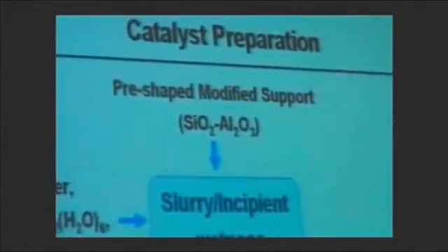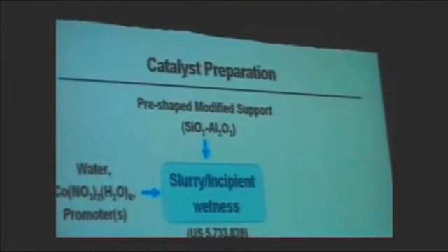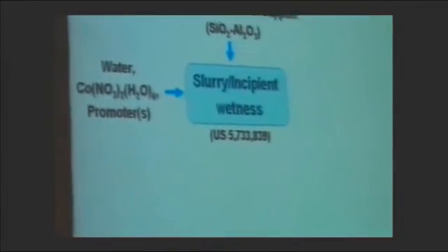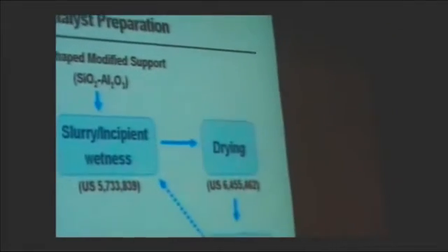Typical way of how you can prepare a catalyst, you start with your pre-shaped modified support, bring that in contact with your cobalt 2+ source, which in this case is cobalt nitrate hexahydrate, through a slurry or incipient impregnation mode, followed by drying and calcination, and end up with your cobalt oxide, which is supported. This supported catalyst can rejoin the cycle if you want to increase the cobalt content, and you can add more cobalt to that in successive impregnations, or you can take the catalyst directly into a reduction chamber where you reduce the cobalt oxide to cobalt metal, followed by wax coating and Fischer-Tropsch synthesis.